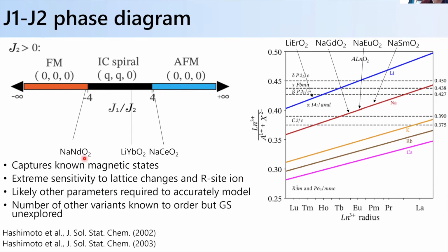The only other fully characterized magnetic ground state within this series of materials with the same structure is sodium neodymium O2 from Hashimoto et al., where it's known to be a ferromagnetic state. And that just involves flipping the sign of J1. Basically further developing this phase diagram is an ongoing thing, but there are many different variants that are known to be stable in this structure type. We also know from thermodynamic measurements that they order, but the order is just sort of uncharacterized. So these would be interesting to explore to try and further refine this phase diagram and what parameters are really essential to capture what's going on as these systems move across it.